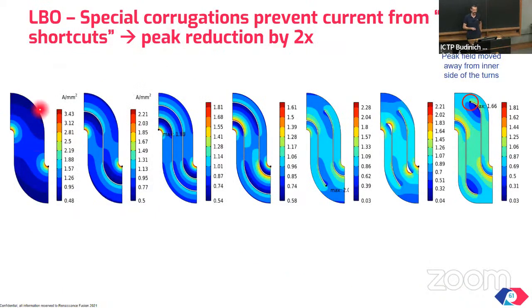Maybe one quick comment: in addition to the main corrugations, this is a piece of the serpentine, by the way, so you have to imagine this mirrored and periodicized. If you now do grooves inside the serpentine, you avoid points of accumulation of current. Current in superconductors takes shortcuts just like in regular conductors, of course. It's a different type of shortcut. They don't take the path of minimum resistance but the path of minimum energy, which sometimes is counterintuitive. They tend to cut corners, slalom as closely as possible, and accumulate at these locations. And you can reduce that by properly guiding the current with proper grooves inside the main path.